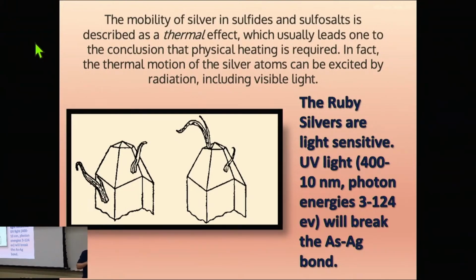And I can't stop this process once it starts. So as soon as I shine a light on this, I'm starting a reaction. If I grow some silver out of that, I have a charge imbalance, and the proustite's going to eventually decay, no matter what. So you have a choice. You can always take the proustite you have and hope that it's never been exposed to UV light, and you could put it in something that has no oxygen environment, store it in a nitrogen container, and it will last a long time. But if you keep it in your case, eventually it's going to turn color, and there's nothing you can do about it. You can't reverse it. You can't shove the silver back in it. But the color is so great, it's the reason we collect it.